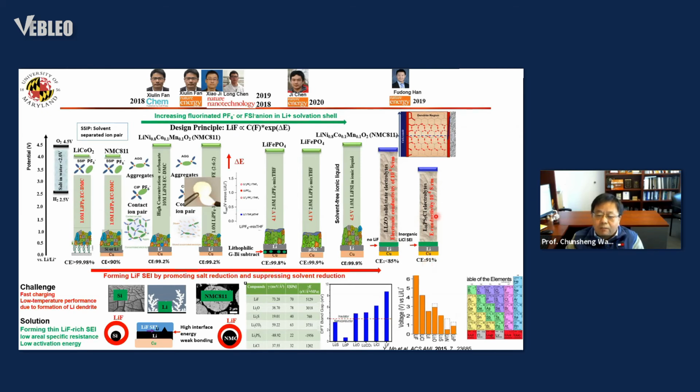So the challenge for solid state is that if you form artificial lithium fluoride, it's not very useful because they cannot self-heal. Lithium penetrates, and then it can directly react inside the bulk solid state electrolytes. So we have to modify the solid state electrolyte itself, form a lithium fluoride rich SEI when lithium reaches the solid electrolytes. Then we were thinking, is there any idea from the lessons of success on liquid electrolytes that can be used for solid state?